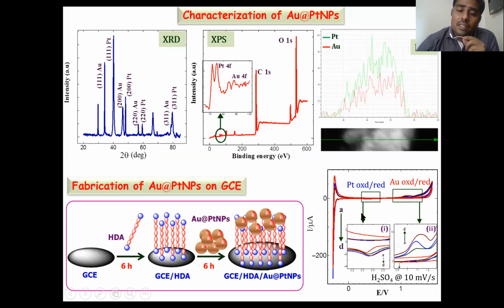The platinum nanoparticles fabricated electrode exhibits the hydrogen adsorption and desorption peak with the platinum oxidation and reduction peaks. After the fabrication of gold platinum bimetallic nanoparticles, the fabricated electrode exhibits the gold oxide formation and reduction peak, as well as the platinum oxide reduction peaks along with the hydrogen adsorption and desorption peaks.